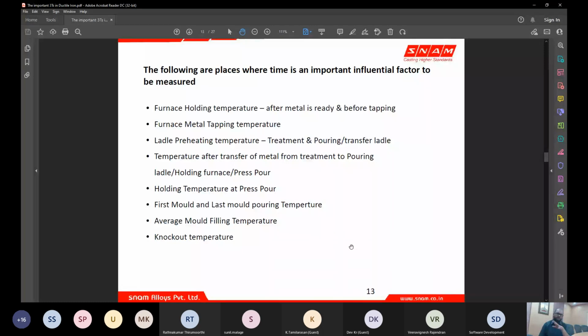When we preheat the ladle to a greater extent, there will always be some slag or some residual liquid metal stuck to the walls of the ladle. And when you preheat it to the maximum level, you start getting reactive products. You start melting the material which is stuck to the wall of the ladle. The material stuck to the wall of the ladle is generally slag, oxides or sulfides. So when you preheat to a very high extent, these sulfides start coming out of the slag or whatever material is stuck to the ladle.